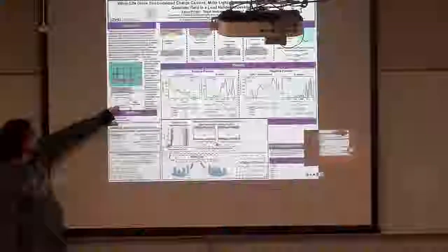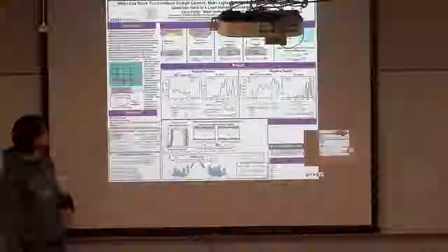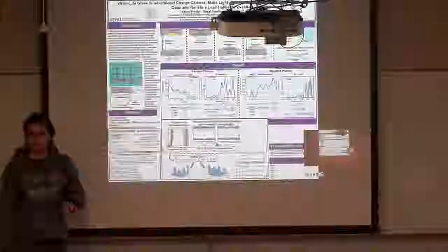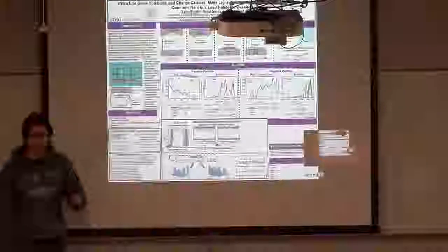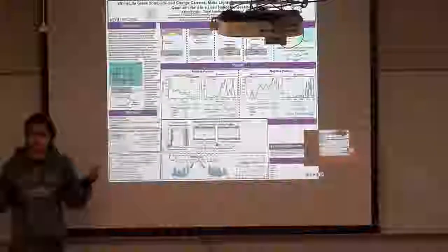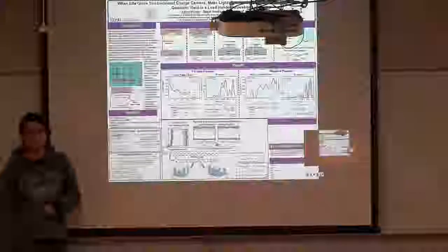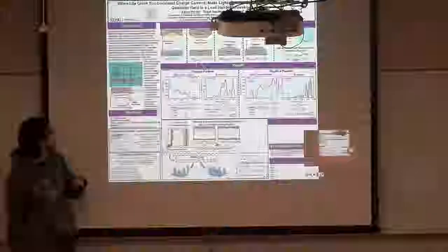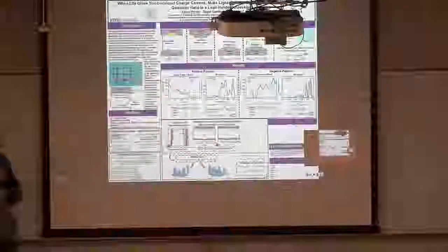And then for the polaron formation, polarons have bound states. In the spirit of Wannier-Mott, you can approximate those bound states as an electron interacting with the average ionic charge that's moved around it. So it's kind of like the Coulomb interaction. You can see the energy spacings will ideally follow the same type of trend. We have our electron at the lowest bound state, and then the bound states take on hydrogenic wave character.